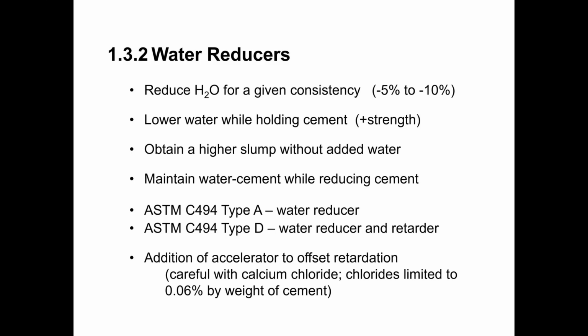Calcium chloride is a very effective accelerator, but we generally try to avoid adding any chlorides to our concrete mix, especially if it's a pre-stressed concrete element. We have a pretty strict limitation on the amount of chlorides that can be introduced into the mix. So if we are going to use an accelerator to offset the retarding effects of a type D water reducer, then you need to make sure that the accelerator that you're using is not introducing chlorides into your concrete.